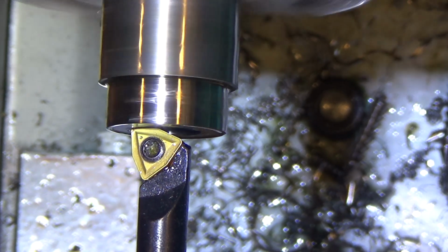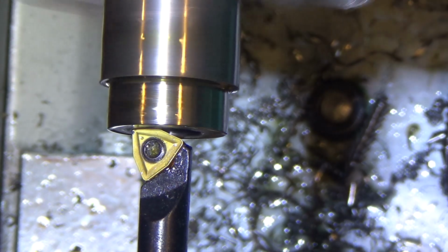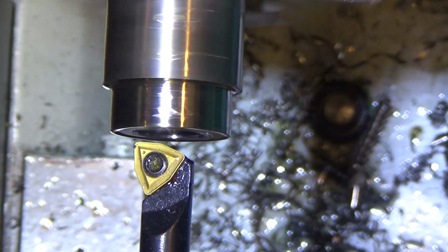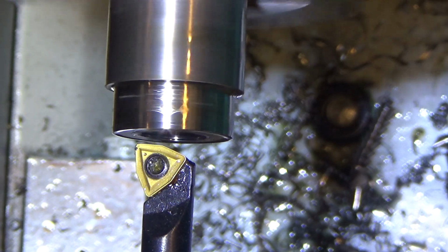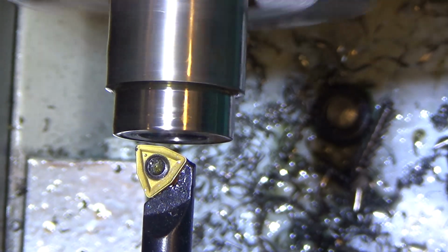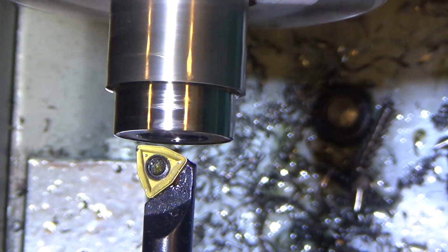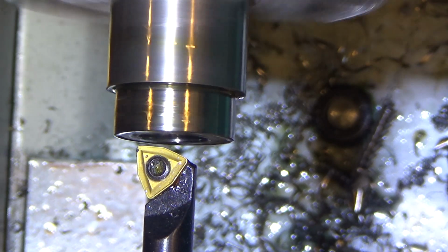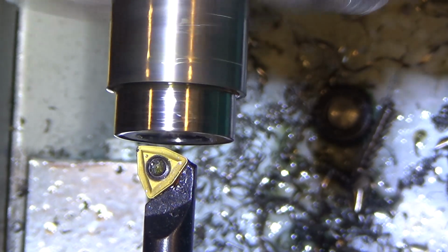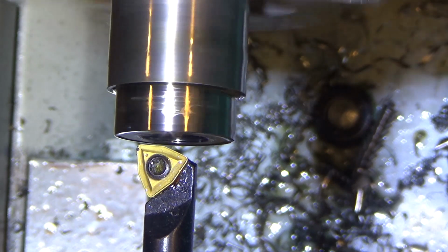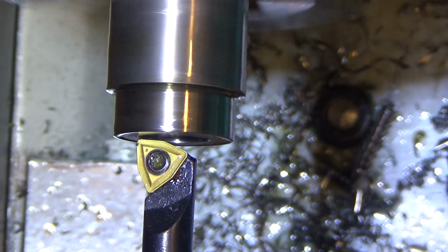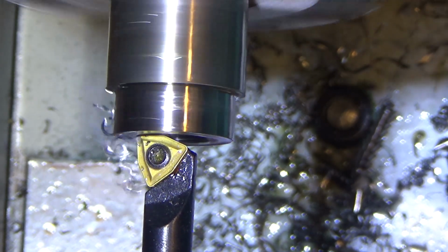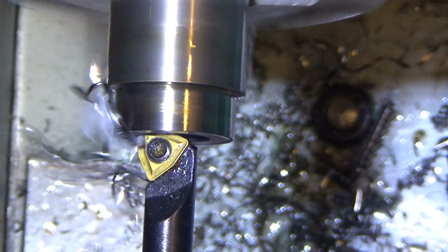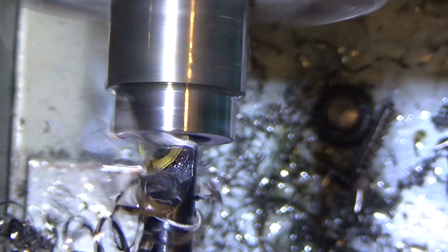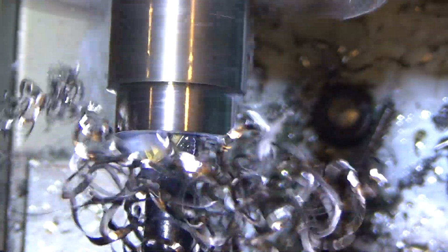So here's some titanium being bored. I had taken some shots of it being drilled, but the camera decided the swarf was a lot more contrasty and focused on that, so the shots weren't any good. It was extremely hard to drill. By the time I got up to ½ inch, it really took a lot of force, and it was getting really hot, so it was burning the lubricant I was using. Hence, again, the need for significant amounts of coolant when you're machining titanium.